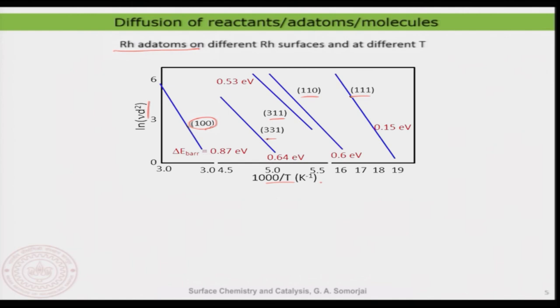Now, the slope directly gives me the barrier, and you see something quite interesting: the 100 surface is surprisingly the surface where the diffusion barrier is the strongest. What does it mean? If the diffusion barrier is the strongest, the diffusion is slow on that surface. But now look at the 111 surface. That's quite interesting. The diffusion barrier is very, very small. So at room temperature, the 111 surface is going to look like all the atoms are moving all the time. But the 100 surface, since it has the highest diffusion barrier, is not going to be as dynamic a surface as the 111 surface.